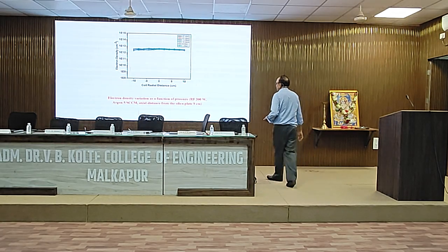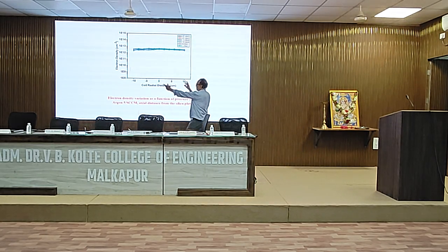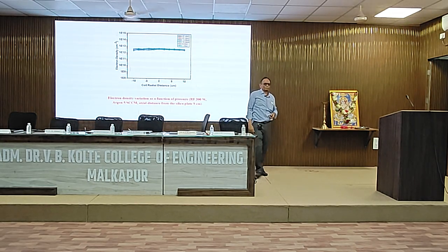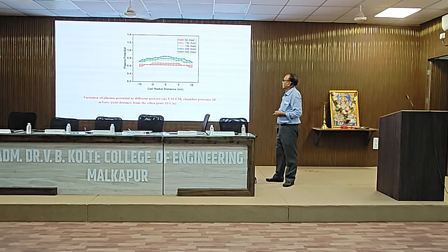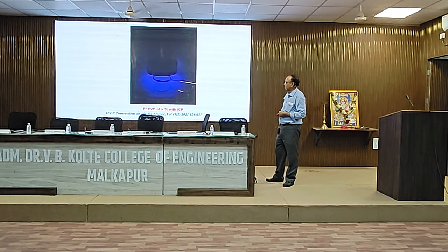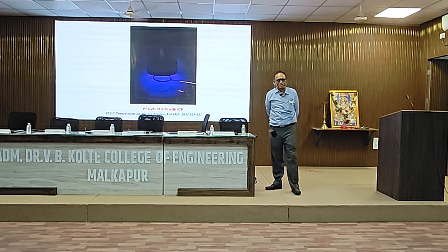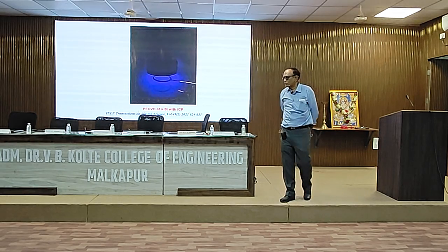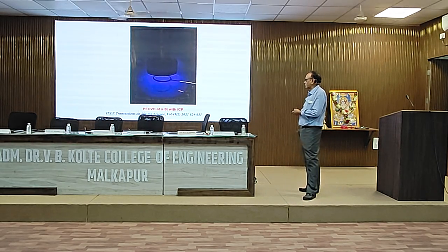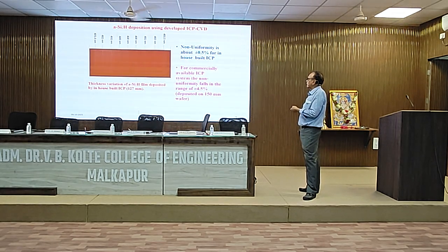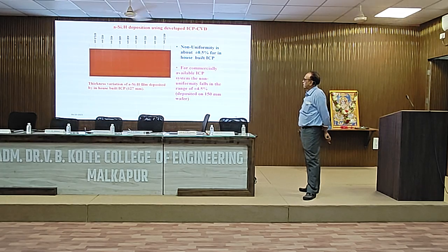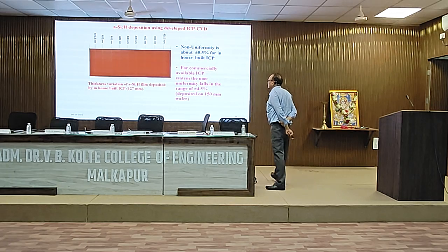Electron number density, you see from the center on 20 centimeter diameter, that means on 8-inch, the number density of the electrons in the plasma is very uniform. And again, there were questions raised, okay, these are all measurements, what about the actual deposition? This is the one in which amorphous silicon thin film is deposited using inductively coupled plasma. With the same facility, results are published here in IEEE Transactions on Plasma Science. And this is on 6-inch diameter substrate, amorphous silicon. You see the uniformity of deposition.